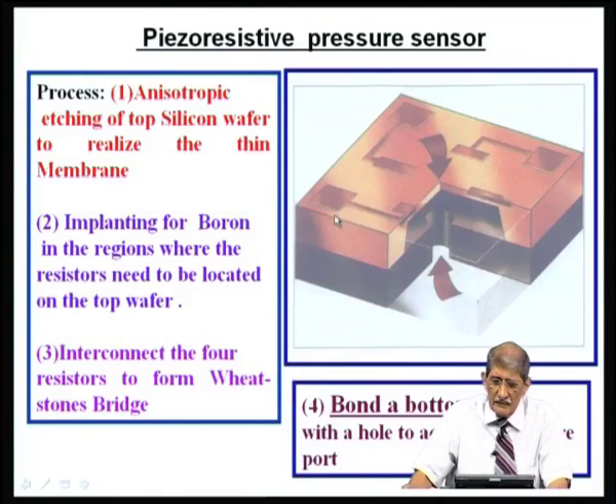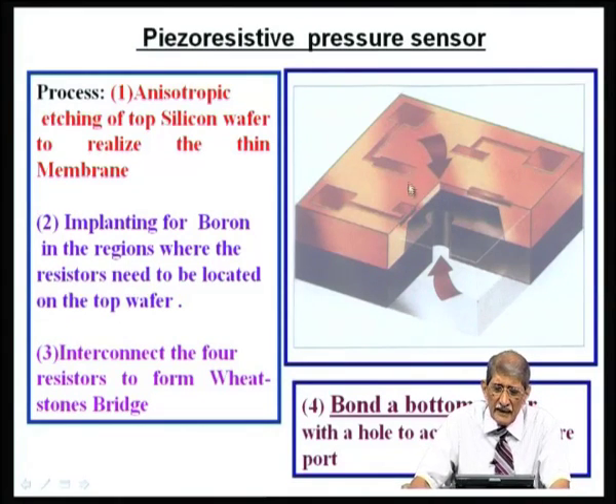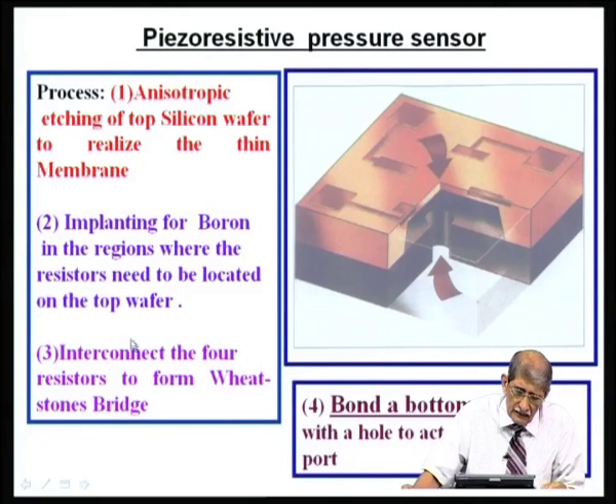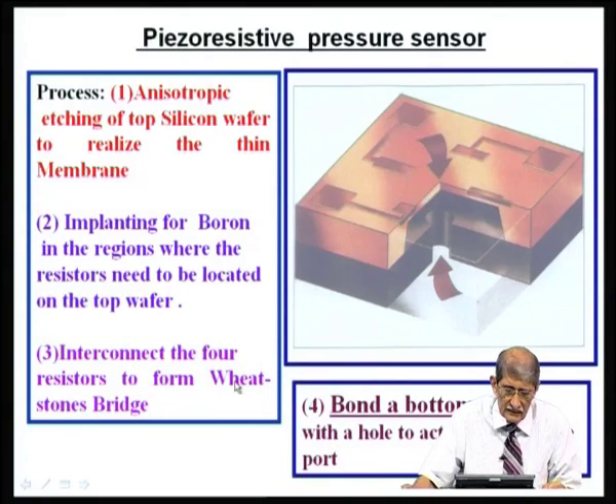Now, this is the pressure sensor, which is a 3-dimensional picture. You put these 1, 2, 3, 4 resistors; the cross section is shown here. This is anchored in these portions. This silicon membrane is stuck to this glass at these edges, so that this is rigid and this can only move. The way you make that is: make a membrane, realize these resistors. First, anisotropic etching of the silicon wafer to realize the thin membrane, implant or diffuse boron into these regions to realize the resistor. Then interconnect the 4 resistors to form the Wheatstone bridge, then bond this glass onto this.